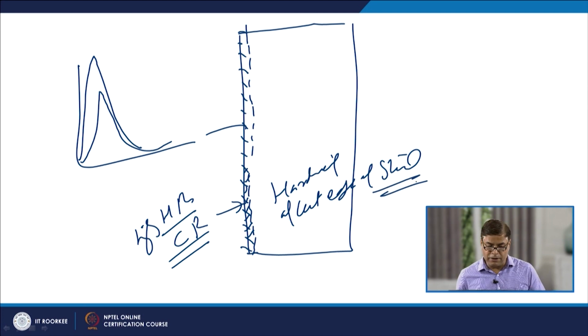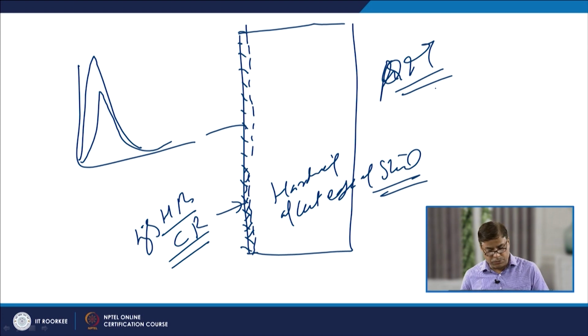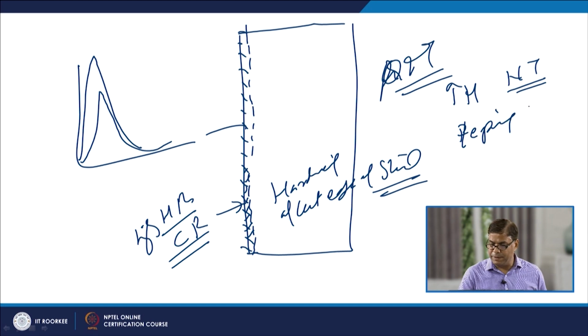So, normally QT steels, when subjected to even higher cooling rates, offer quite a good combination of microstructure. So, despite the increase in hardness, the toughness or notch toughness is not very badly compromised, but still whatever toughness is there, if that is not sufficient for a given purpose, then we need to apply tempering, a post-cutting tempering heat treatment.